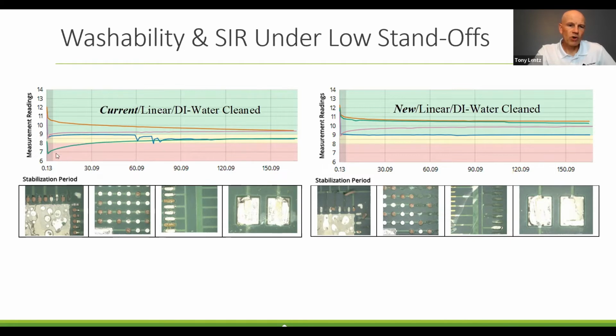And so a couple of those comb patterns actually were below 10 to the 8th ohms here, which is the 8 on the y-axis, which means they technically would fail here at the beginning. And then this yellow band is kind of the cautionary zone between 10 to the 8th and 10 to the 9th ohms in this test.